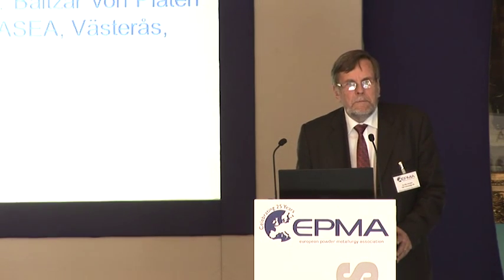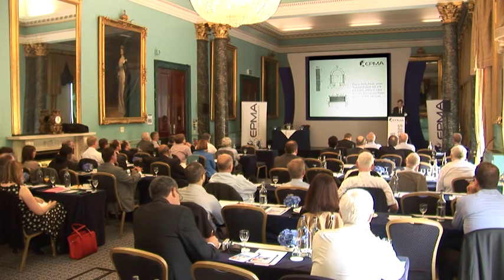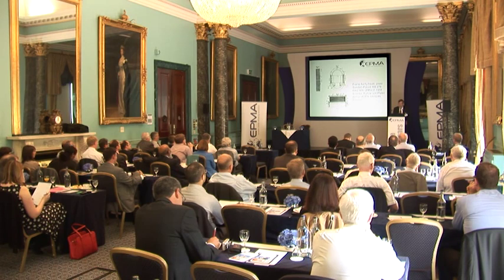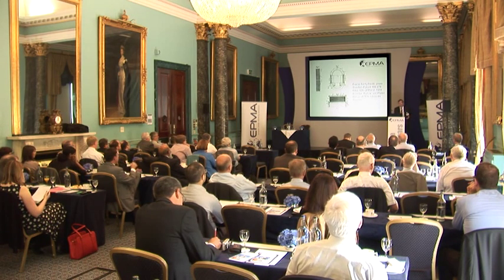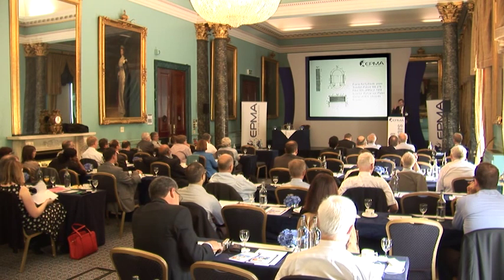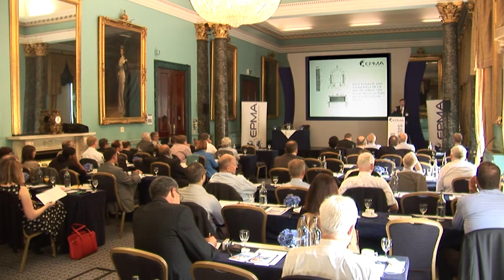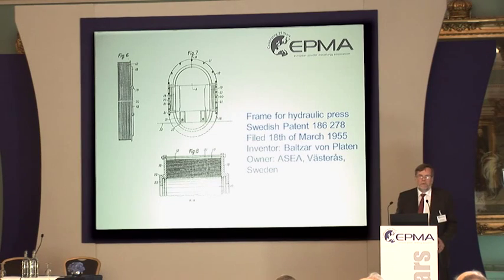And this shows the first patent from 1955. You can see the frame of the equipment is wire wound by high strength, cold deformed steel wires, which managed to give very good stability for the equipment. Important to know, if a monolithic shell is cracked, the hole will go through. If one of these wires is cracked, the load will be taken over by the surrounding wires. So this was a genius invention by Mr. Baltzar von Platen.